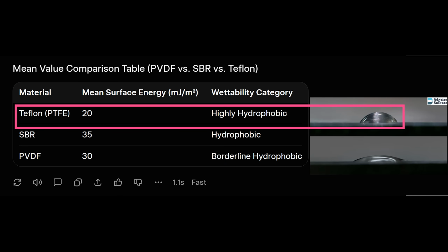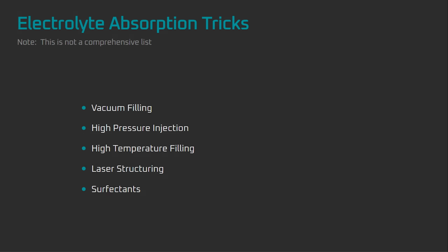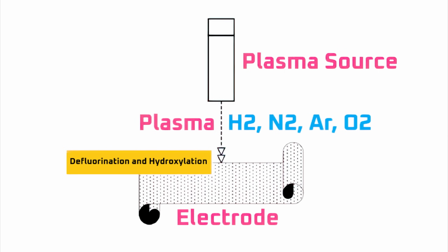In summary, necessity is the mother of invention. The PTFE used in Tesla's dry electrode coating process was likely creating greater bottlenecks for electrolyte wetting than a typical wet coating process because PTFE has a greater tendency to repel liquids. That forced them to ditch the typical methods of improving wettability and rethink the wetting process at a first principles level, which led to plasma treatment.